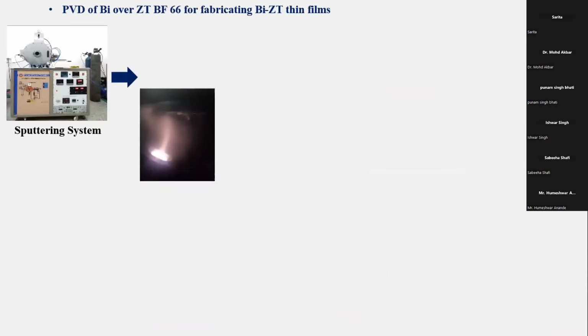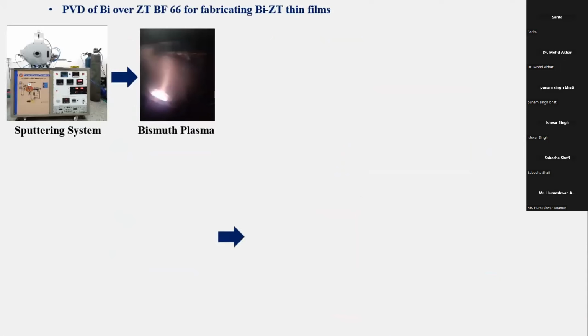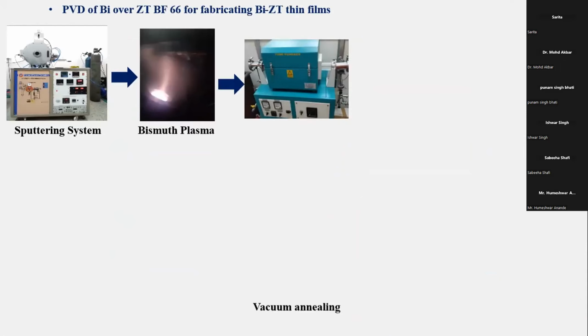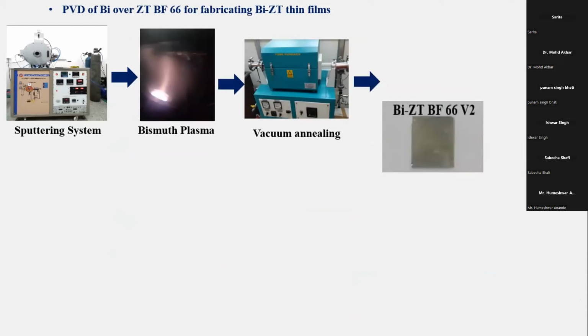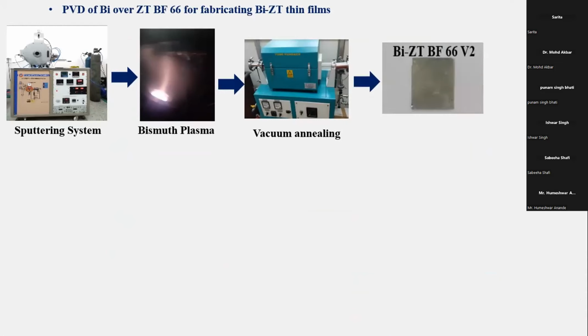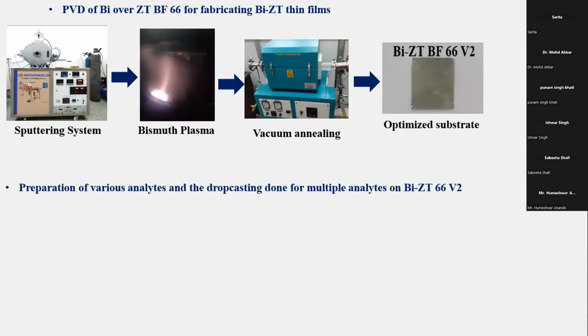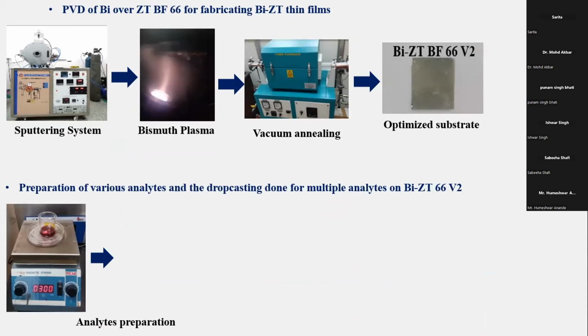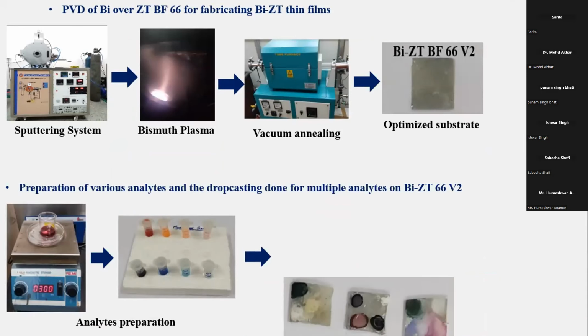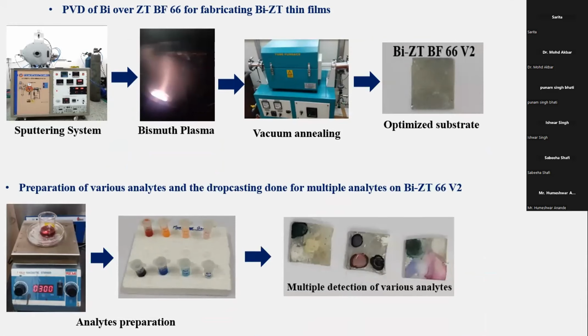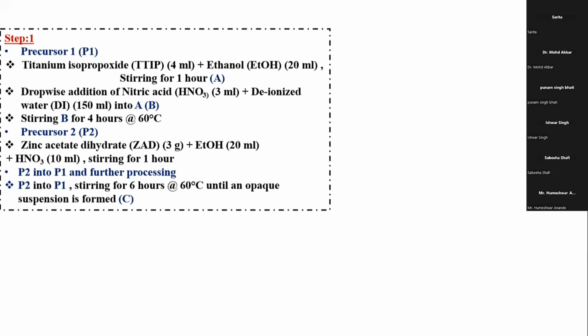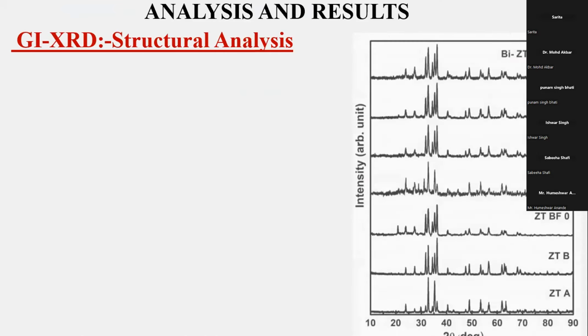On top of which, using sputtering, we use DC plasma of the bismuth to sputter some films, after which we anneal in a tube furnace, and this is the final substrate we develop for the multiplex detection. On this, by the normal drop casting method, certain analytes were prepared, and this is what multiplex detection normally looks like. These are the fabrication things. I'll go to the results and analysis discussion.